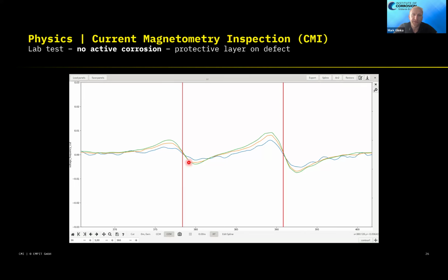So we have 3 frequencies. Obviously, the normal signal contains up to 100 frequencies, and we see we are losing current at each of the frequencies, and we have this nice little zero crossing. What we can clearly see, let's say this blue line is 2 Hz, whereas this greenish line here is 2 kilohertz, that we do have an attenuation dependent on the frequency. So we have a frequency spread. The highest frequency is losing the most amount of current, whereas the lowest frequency is losing the least amount of current.